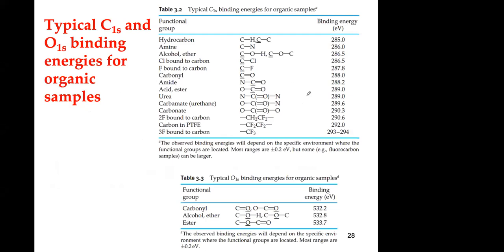And if you look at the carbon 1s signal and the oxygen 1s signal, although the changes are very small, you can see changes in the 1s structure. Usually this is the standard value. This changes from scientist to scientist. Sometimes it's 284.5, 284.8, or 285. And this is what I mentioned previously that you use as a reference, because most of the samples have hydrocarbons on the surface. And you can use that as a reference value to calibrate the x-axis, the binding energy axis.